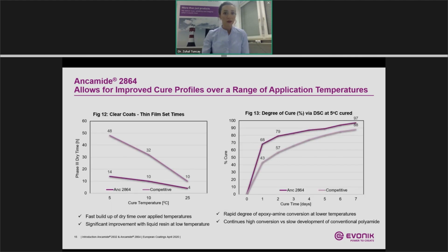Here we can see the difference in low temperature cure profiles. When we run thin film set time using a BK recorder for clear coats, we see a significant difference as the application temperature is low. At 5 degrees, 2864 reached the third phase after 14 hours, whereas the competitive curing agents need almost 48 hours. And after 48 hours, the film was still sticky to touch.